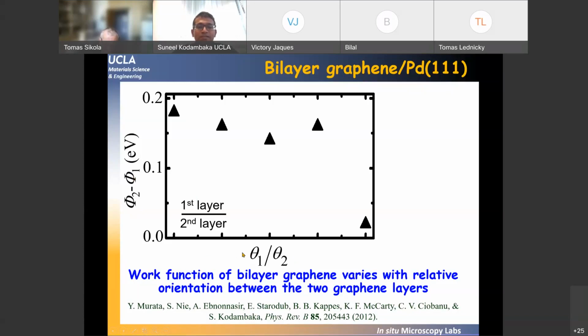Now, there is a lot of information in this plot, so let me walk you through this. All these data correspond to two-layer graphene on palladium. Now, when we grow graphene on palladium, it's growing from the bulk, and so each layer assumes its own orientation without any control. And so this theta 1 corresponds to the orientation of the first layer graphene on palladium. And theta 2 corresponds to the orientation of the second layer graphene on top of the first layer graphene. And here, the phi 2 is the work function of the two-layer graphene, and the phi 1 is the work function of the first layer graphene.